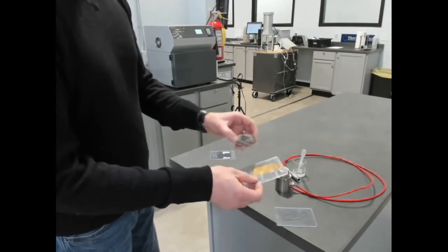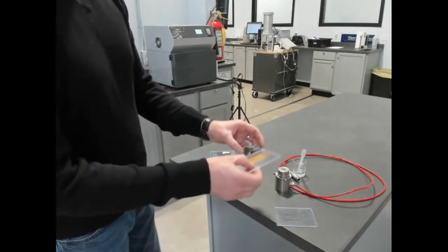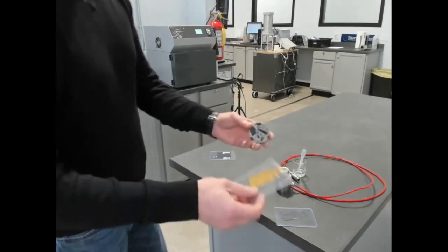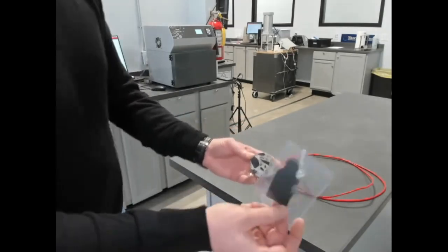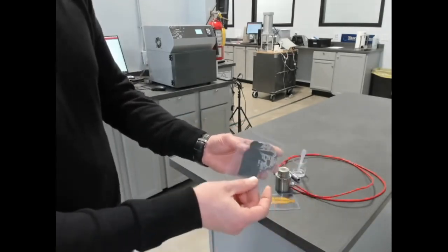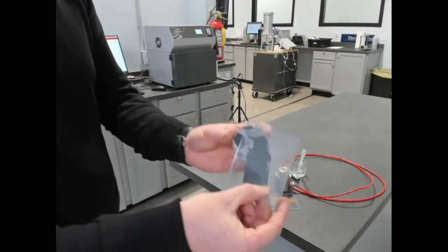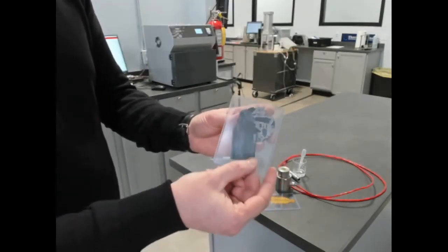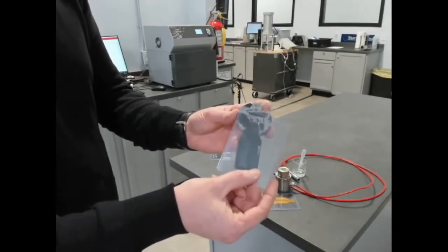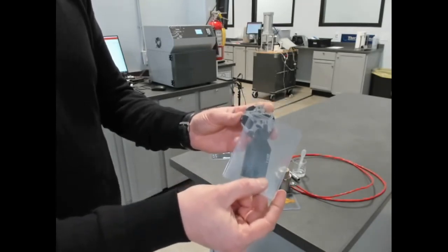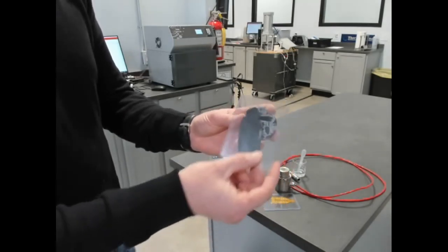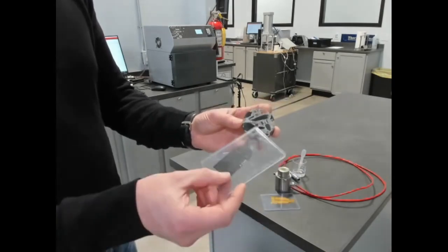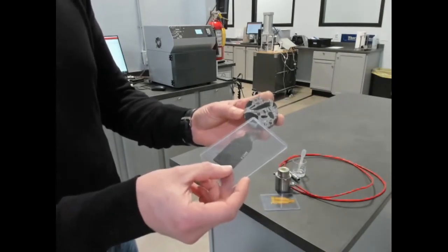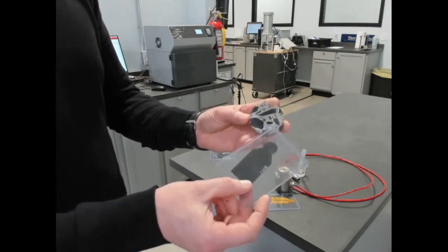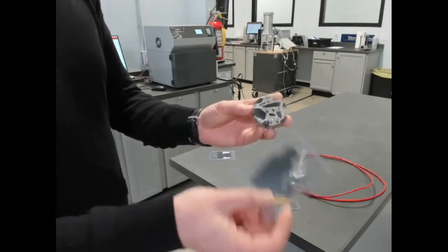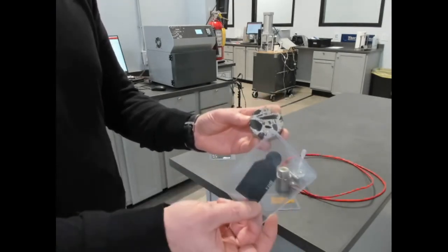Again, the basic theory of transient plane source is that the heat we introduce never leaves the boundaries of the sample. So if you were to take our 13 millimeter sensor and move it around, and this is the same for all of them, you can see that the average value is going to be ever changing. So even if you do 1, 2, 3, 4 locations, those differences between each of those locations are going to be extreme. The rock is probably in the range of 2 to 4 watts per meter Kelvin. Concrete by itself is in the range of 0.3 to 0.8 watts per meter Kelvin. You have all the porosity in between.